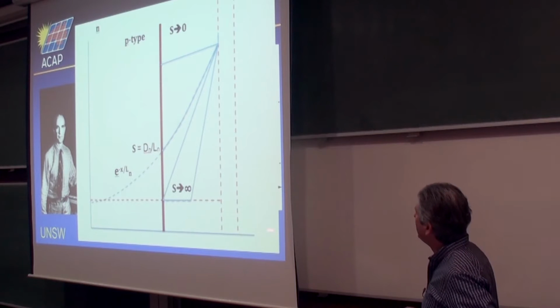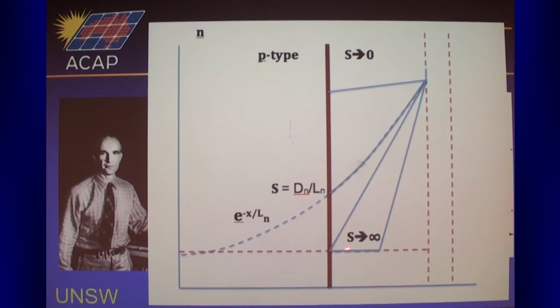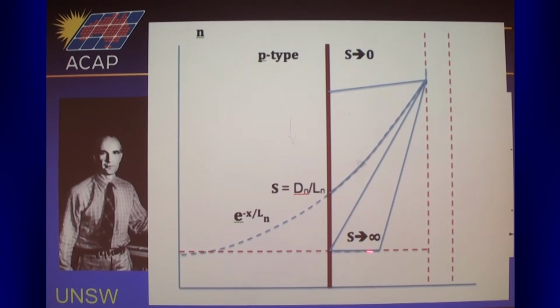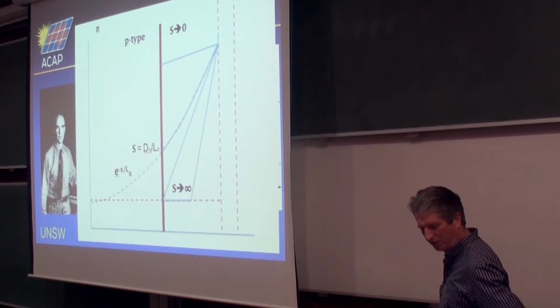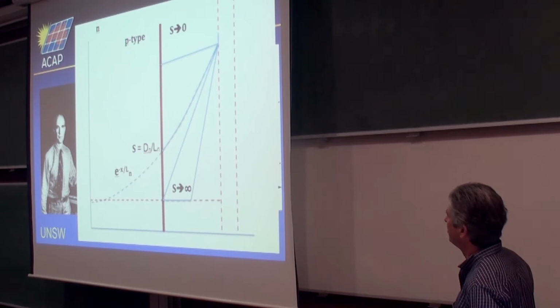If we go back to the conventional cell, it had this dead layer at the surface. So this was more like what happened in the conventional space cell. You had this dead layer where there was just no chance of minority carriers surviving. They just got suppressed to their thermal equilibrium value, but that increases the gradient further, as you can see there. So you've wiped out this region of the cell by doping it too heavily, and that increases the current flows to that region, which reduces voltage.